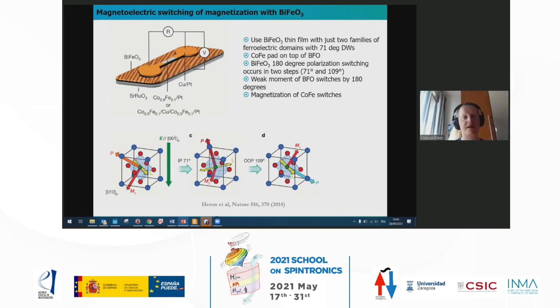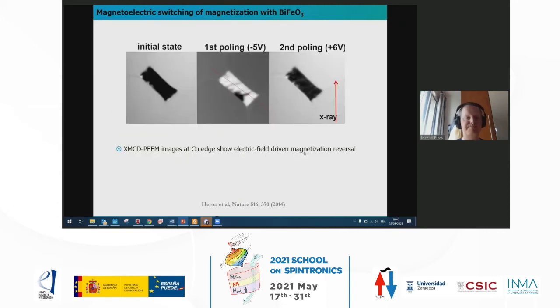Okay, it's a weak ferromagnet, if you wish. So as you do that, you can switch the weak moment of bismuth ferrite by electric field. And these are some XMCD-PEEM images at the cobalt edge that show that the magnetization of the cobalt can be switched one way and back by applying negative or positive voltages.